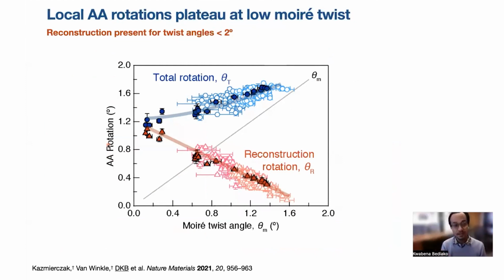And what you find is that because of this relaxation process, below about 1.6 or 2 degrees, the total AA rotation is more or less constant, pinning to a value of about 1.2 degrees or so. Whereas at larger angles, it would follow this gray line, and the total rotation would more closely match the Moiré rotation.